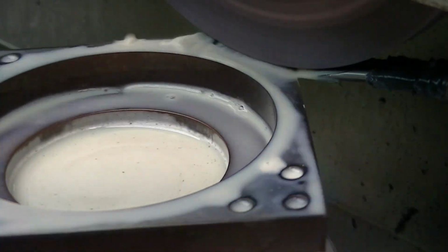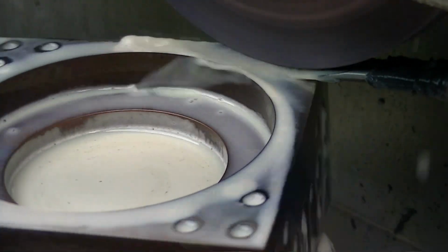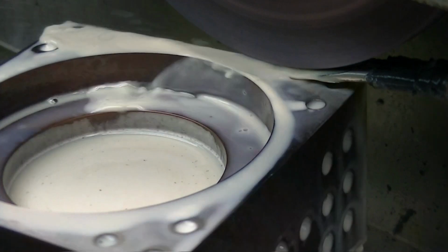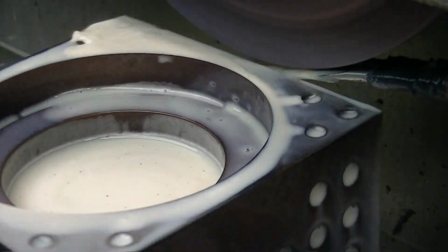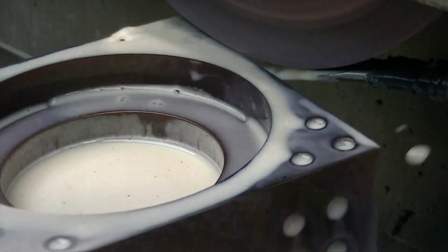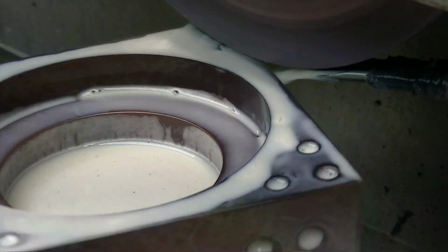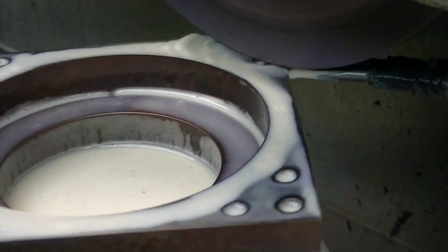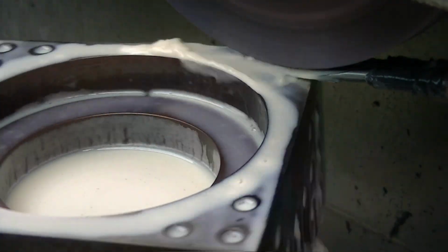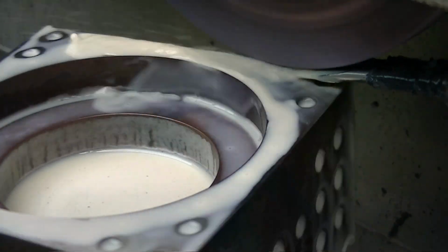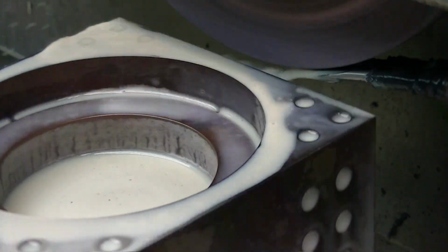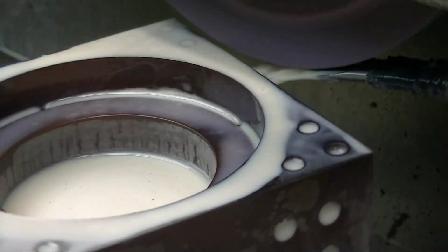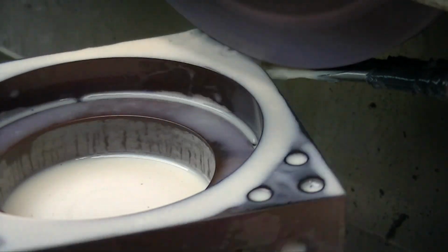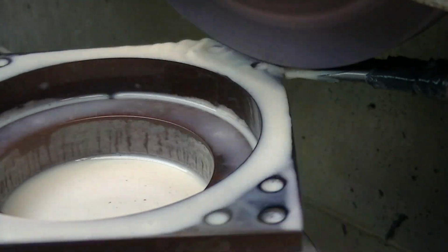For the final passes, I slowed my rotary speed way down, and what that does is it lets whatever amount of out of balance there is still left in the wheel, even after balancing, it allows the scallop from that, basically the high point touching, which still shows up unless you're absolutely perfectly balanced, which this isn't. It's balanced very well, but not to the point where you don't have some hop showing.